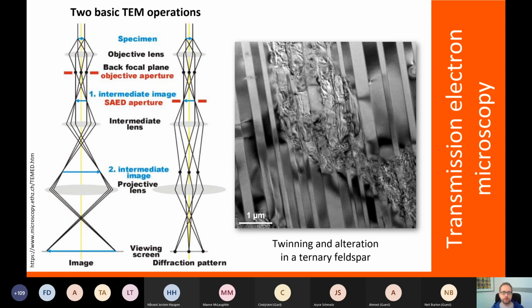What we need to know is that there are two basic TEM operations. First of all, in a TEM, our electrons are coming in parallel onto our sample, in this case called specimen. And we can form an image on our screen. And here on the right-hand side, you see, for example, a bright field image of a feldspar that shows twins. You can see this here. So the different twins diffract differently. The paths of the electrons have changed. You get this diffraction contrast, and you have an alteration zone here in the middle. This is the imaging part.